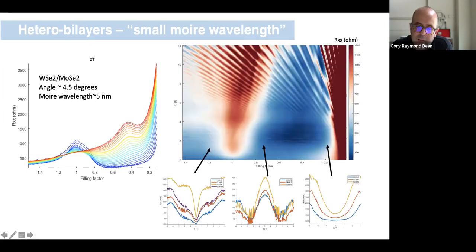And in particular, the last thing I just talked about: if we look at magnetoresistance in this system, we see that the magnetoresistance shows a similar evolution to what we observed for our homobilayer systems. So at slightly overdoped from the half band insulator, we have a positive magnetoresistance in XX. As we go to underdoping, that transitions to a negative magnetoresistance. And if we go further underdoped, near the band edge, we recover again a positive magnetoresistance.